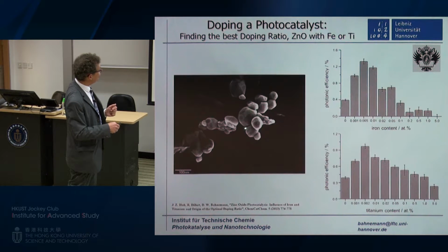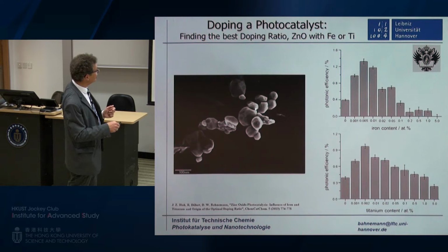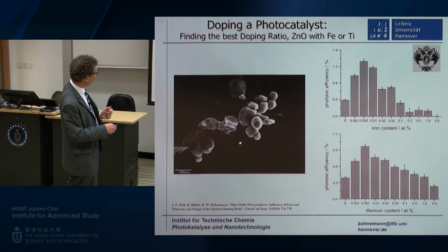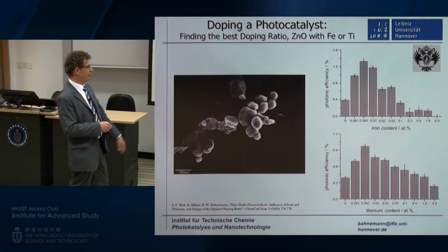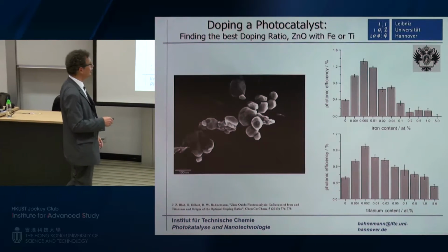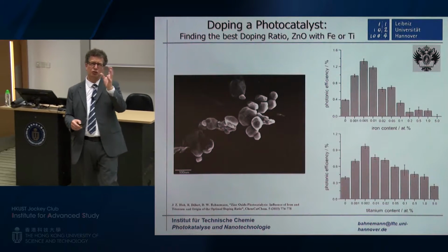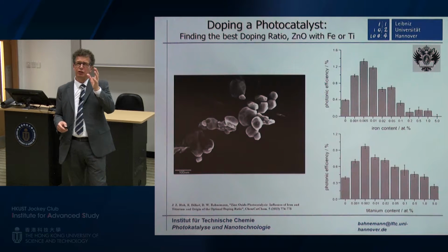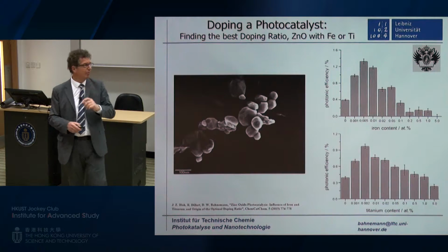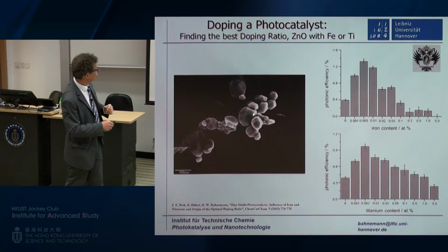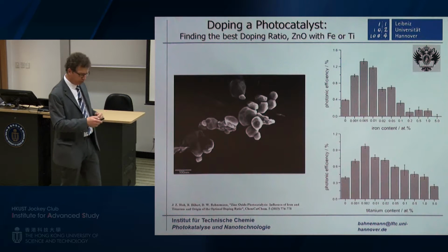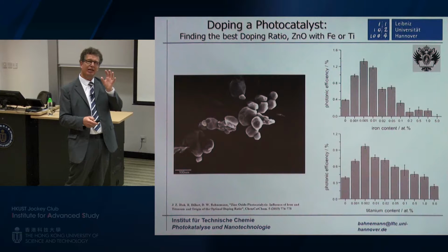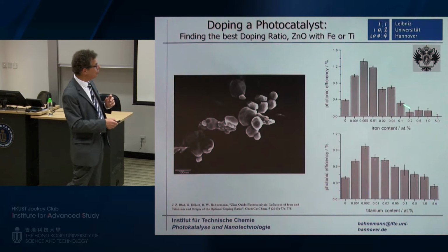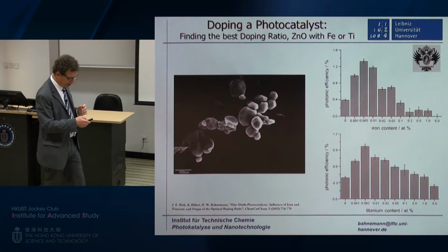Well, when he looked at the zinc oxide particles he had prepared, this is 100 nanometers, pretty big nanometer-sized particles. The ones I showed you before with the TiO2 were in the range of 3 to 4 nanometers in diameter. Here we are talking about 50 to 100 nanometers in diameter. So diameter seems to have something to do with the amount of dopants needed.